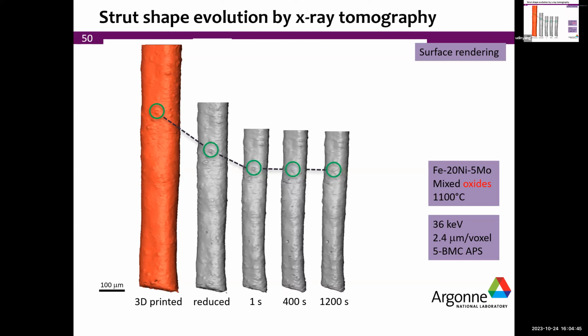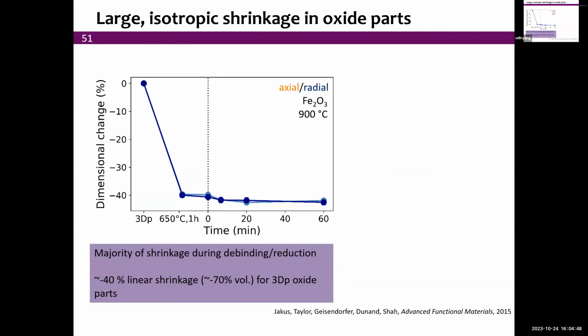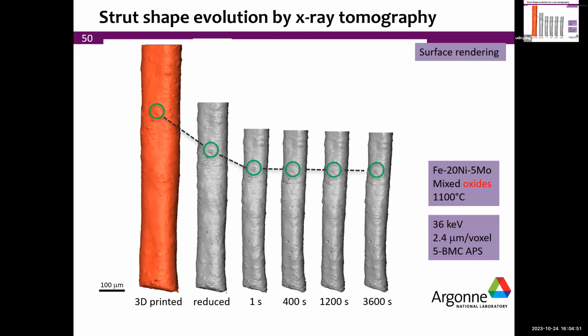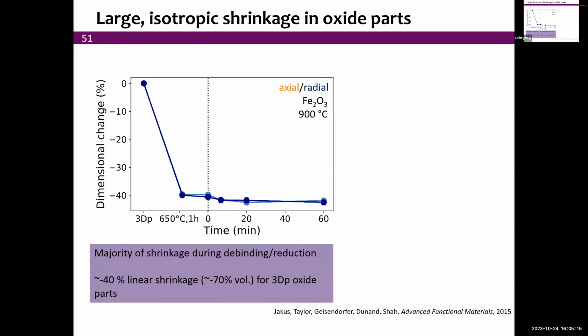And as you now sinter to longer and longer times, all the way to about 1 hour, most of the sintering happens after only a few seconds at high temperature. So this is this alloy using mixed oxide, sintering very quickly at 1100 degrees C. Technically, the reason why we're waiting here is to make sure that we have full interdiffusion between the various elements. And you see that the dimensional changes, of course, happen right away. That's the pre-sintering.